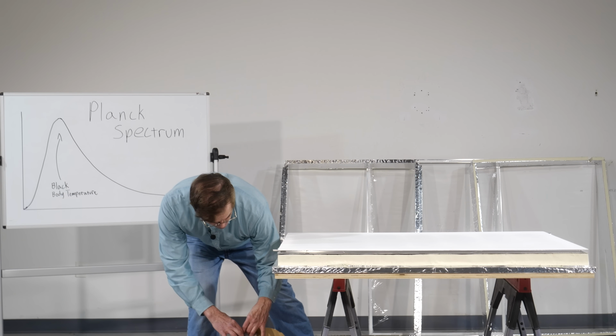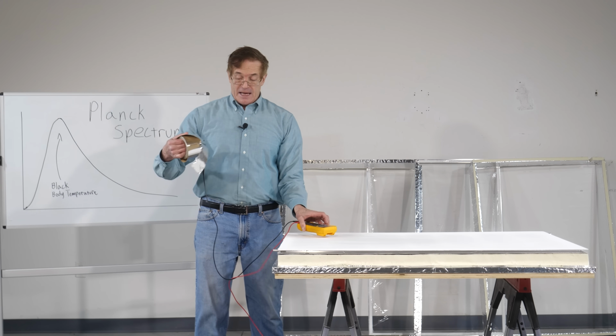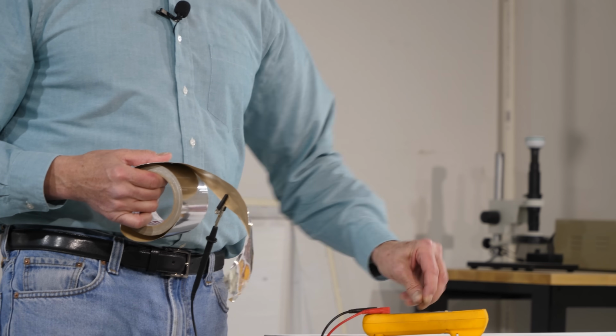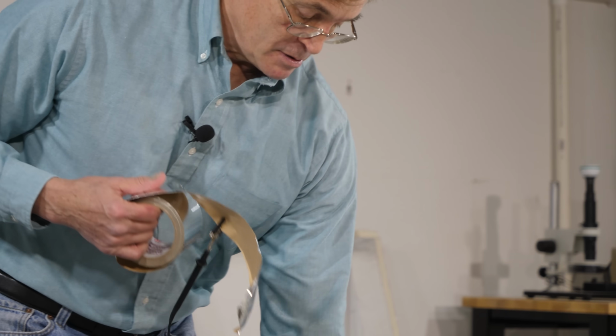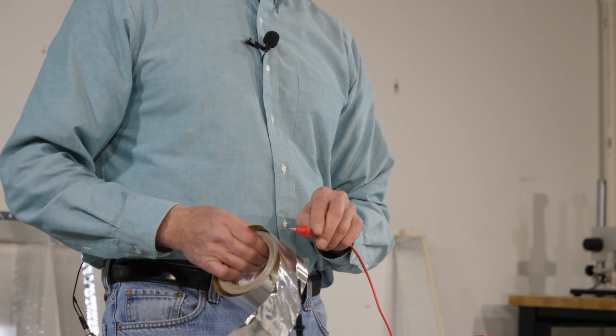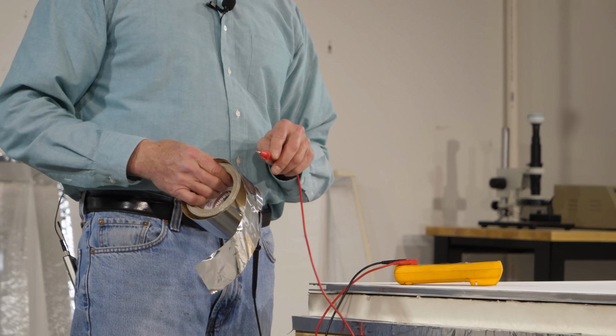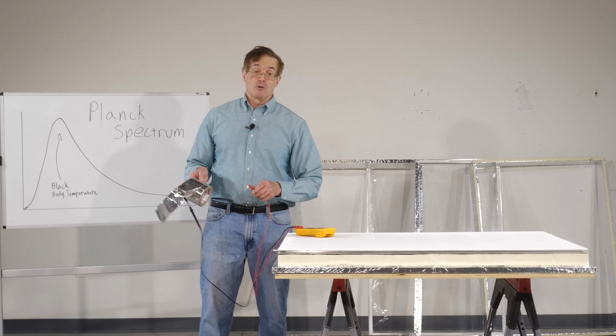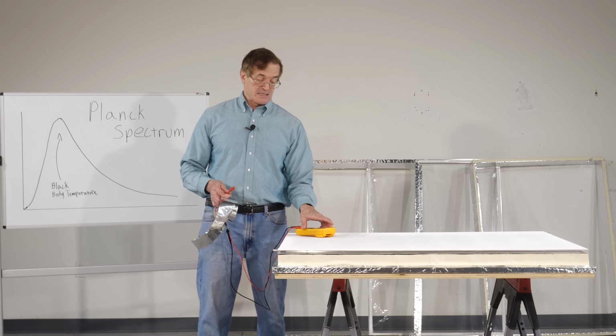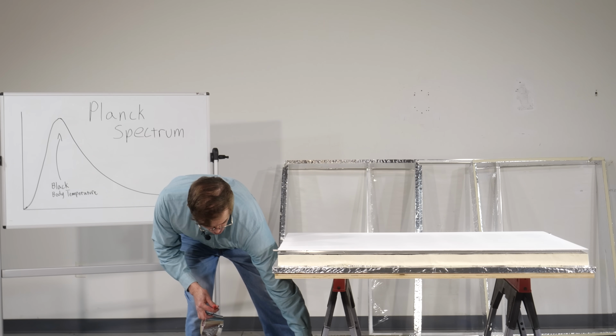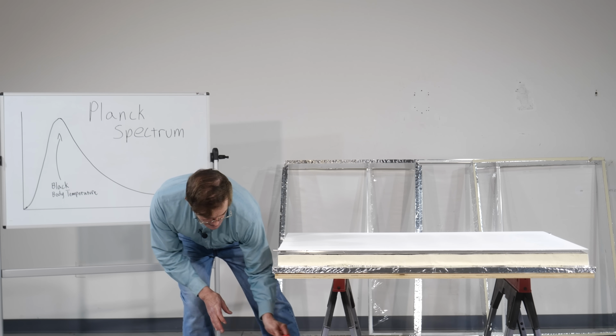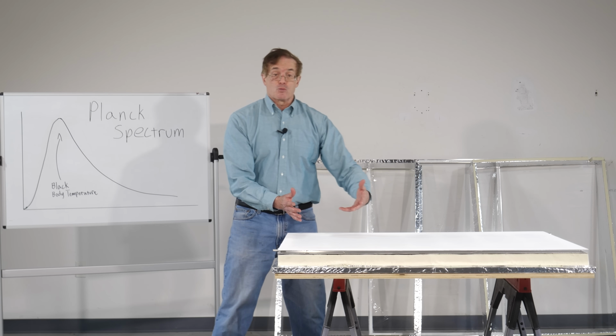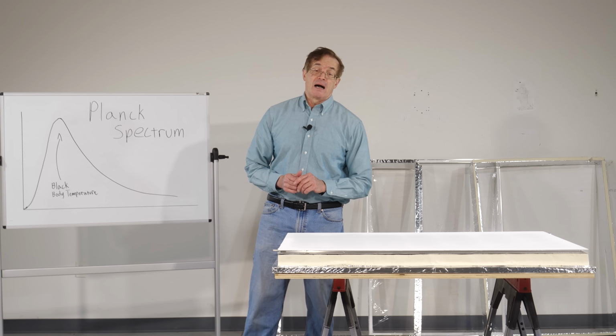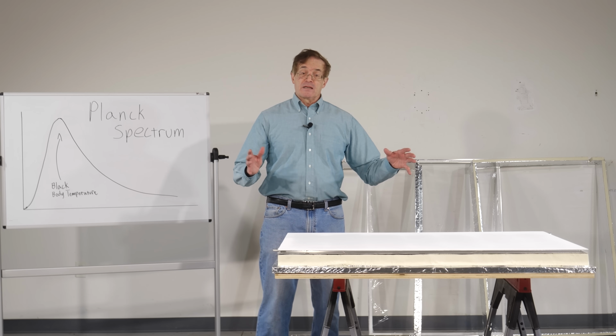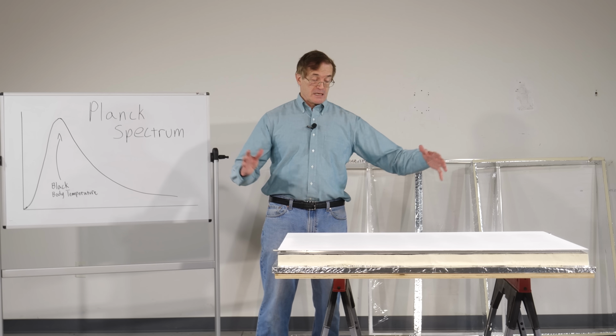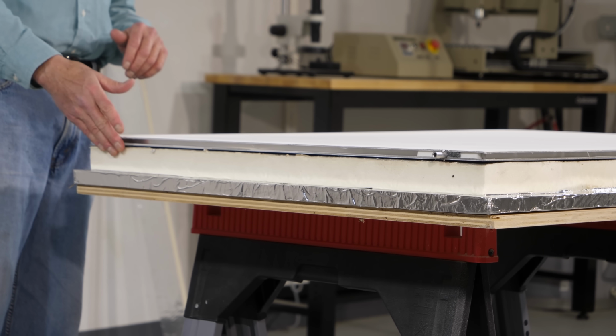This tape that we use for this purpose is not just colored as aluminum. It's pure aluminum. It has about 6% emissivity in the infrared. The result is that by surrounding this radiator surface with this insulated box, we're able to isolate it from the environment and also prevent infrared from being radiated down onto this very specialized surface.